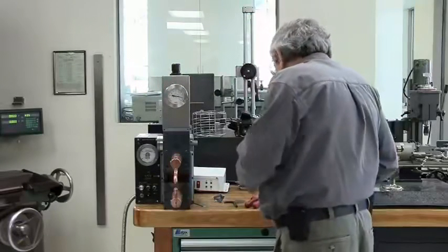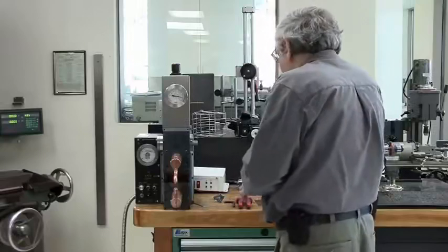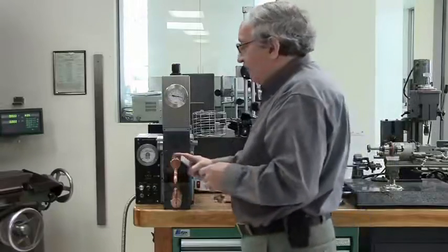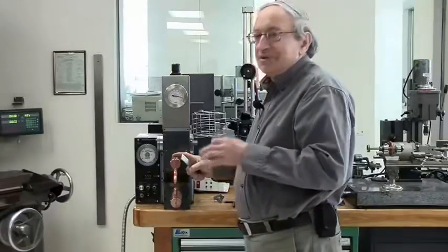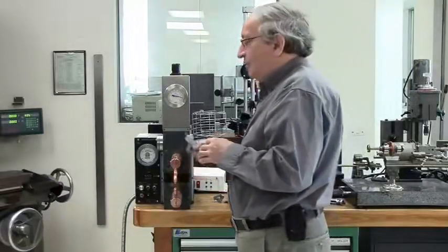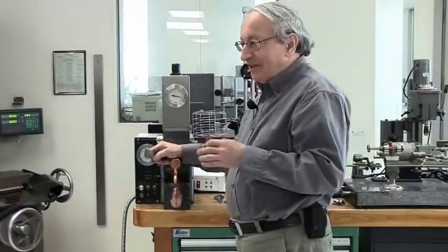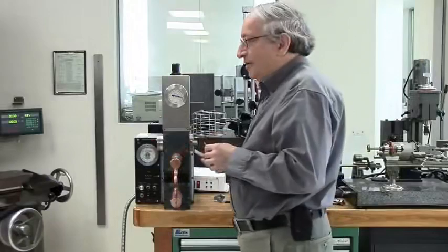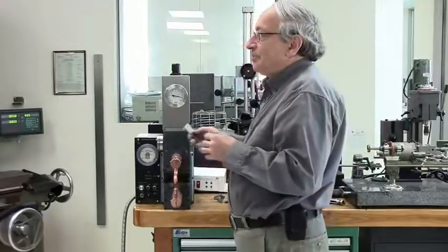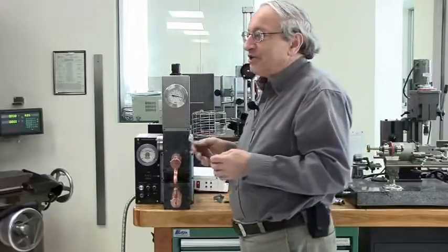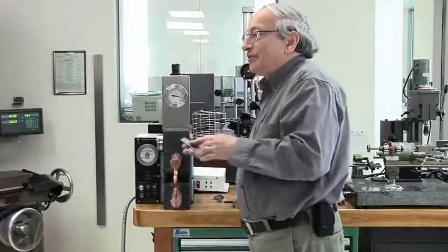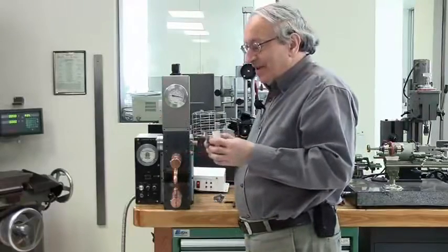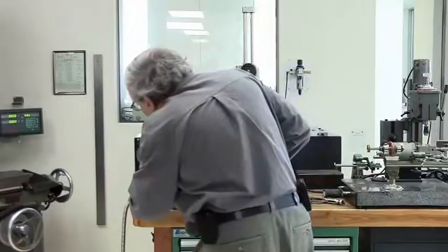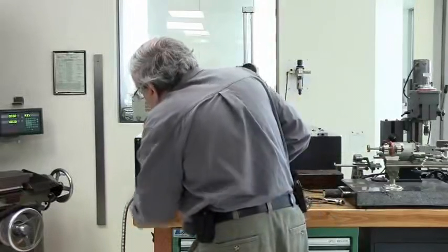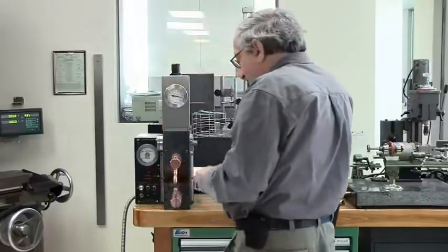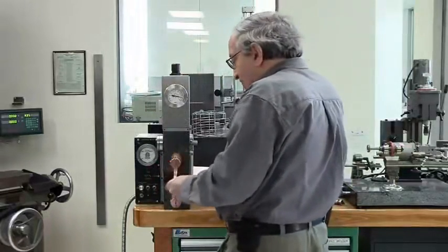Okay. So now this one, as I mentioned, is a 15 kVA unit, and that's about the minimum you want. You want a unit which is anywhere from 15 to 25 kVA. So 15 kVA will weld something like 3 millimeter to 3 millimeter, or if you're used to gauges, it will weld like a gauge 12 to gauge 12, or gauge 10 to gauge 10, and that's the limit. And for that you need something in the order of 15 cycles, I think. And that's it. It wouldn't take any thicker stuff. So let's try that. That's about gauge 12 steel.